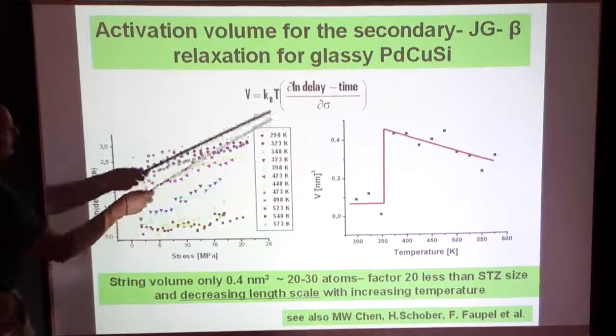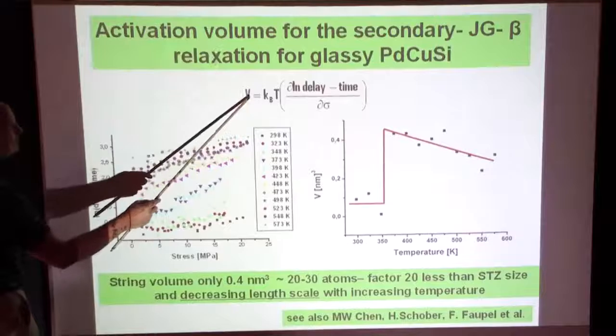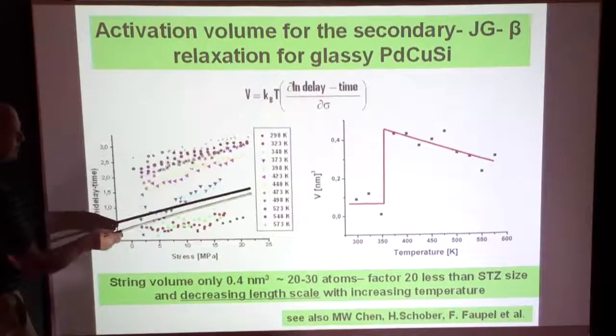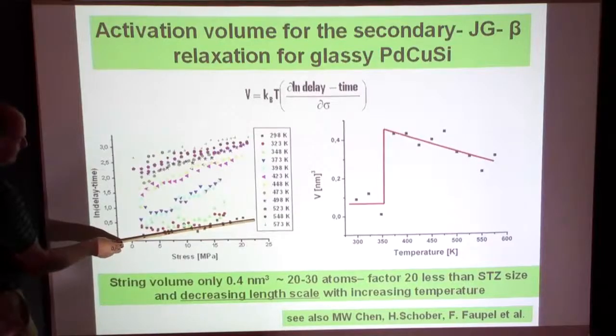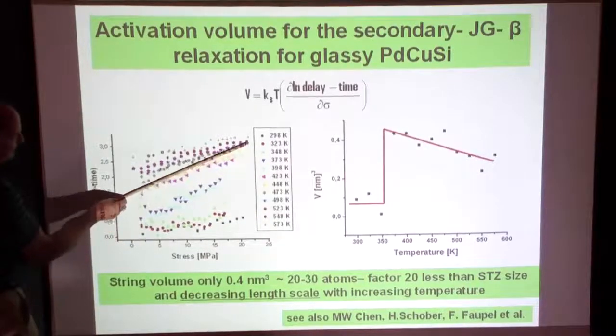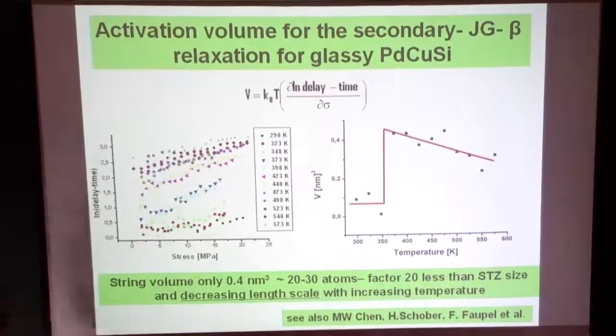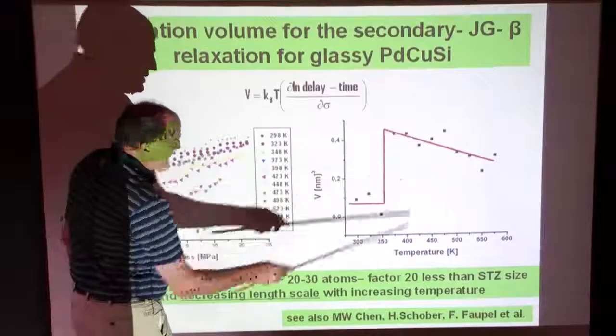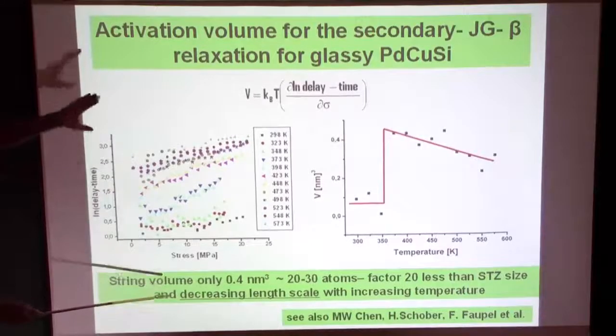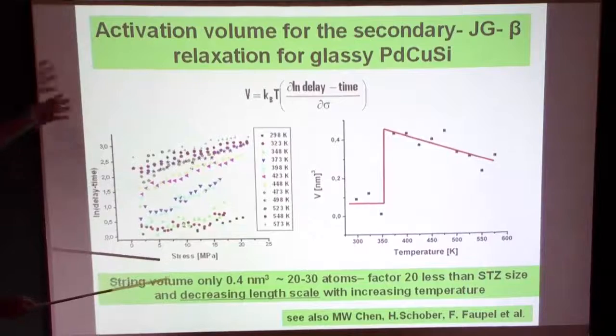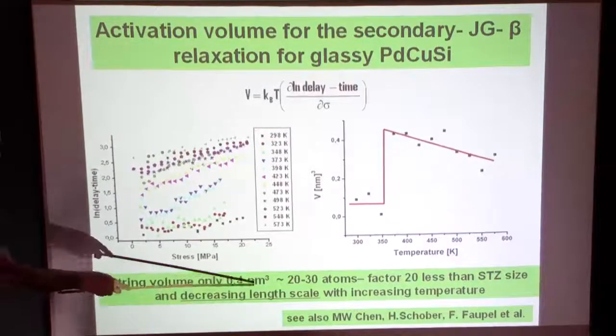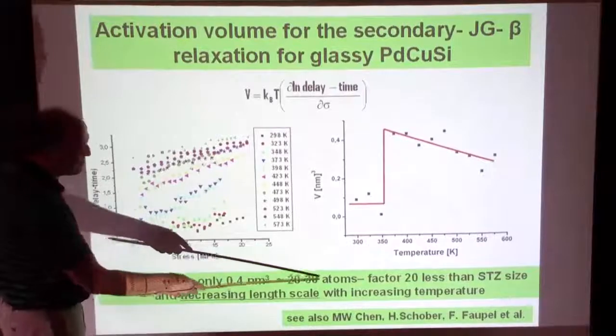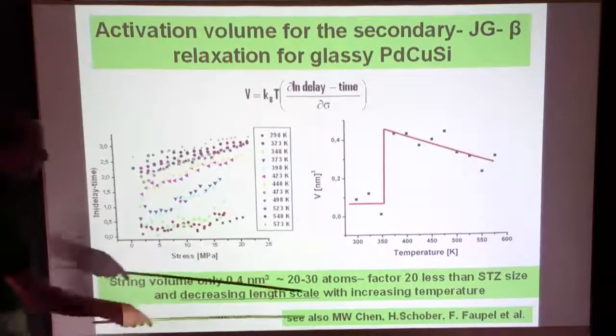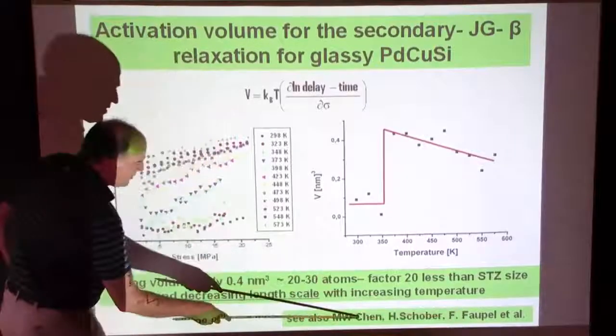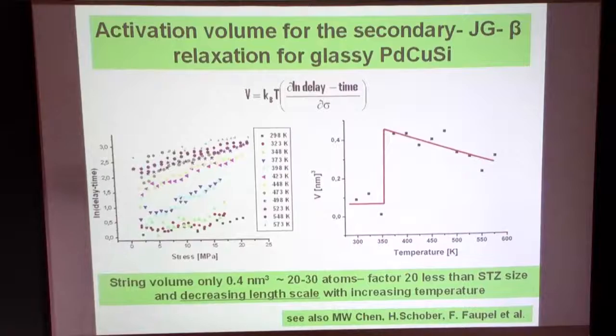You have a certain curvature, and from this apparent activation volume, you can calculate by this simple formula how much volume is activated for that process. You can see it slow down here, and it jumps over here, and even comes down again. So this is the slope, plotted over here, and you put real numbers in. You find that the string volume, since we are below Tg where the alpha process is frozen out and we only have the secondary relaxation process, is about 0.4 nanometer cubed, which is about 20 to 30 atoms. Exactly what people also saw in the simulations, in the diffusion measurements, and also in some surface measurements from the Japanese group.